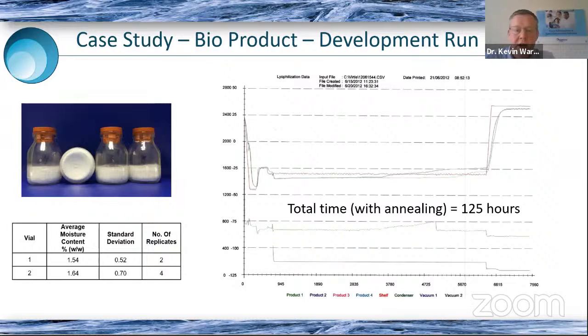And so when we applied the annealing step, we annealed it to -25 and kept it there for several hours to make sure that it would be more thermally stable. We then found that when we started drying it, we could use a slightly higher shelf temperature, and we can reduce the drying time by at least 1 day. So that's a good start, and still achieve the same moisture content as before.